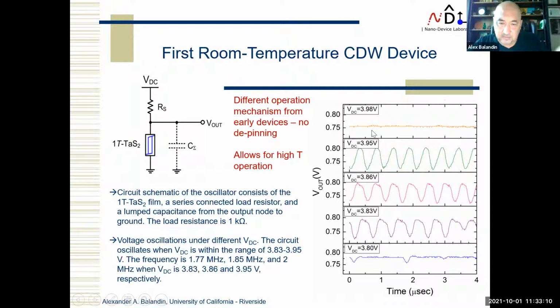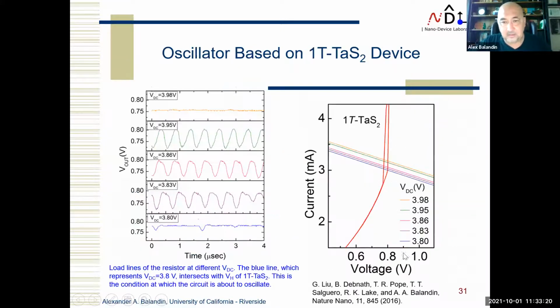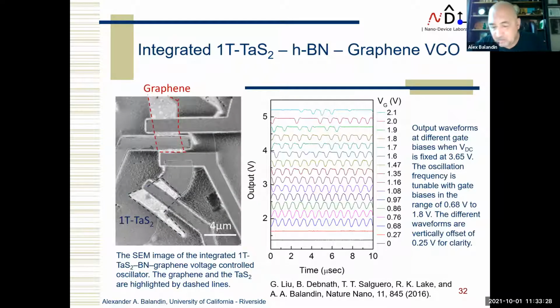And as you can see here, these are oscillations, just gotten from the oscillator. If your bias is not enough, there's no oscillation. When you have enough bias, there is oscillation. If it's too much, there's also none. So you just have to keep your load line within this hysteresis window, and you have an oscillator. In this case, the oscillator oscillates in the megahertz region, but this is limited by parasitics, and in fact, it would be fast.